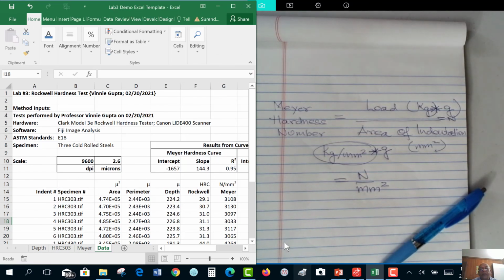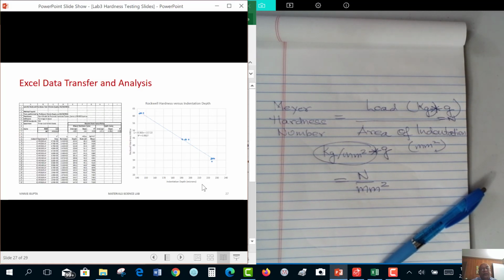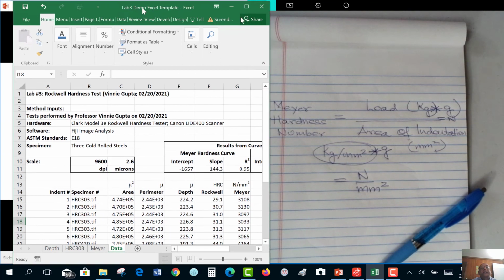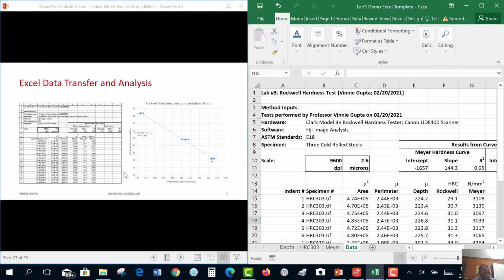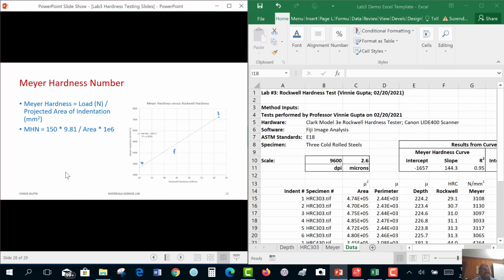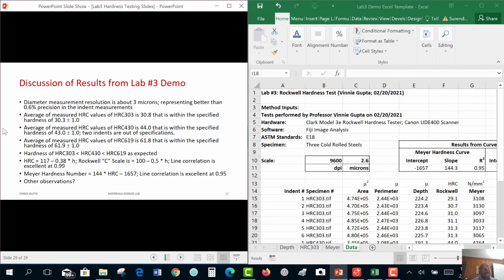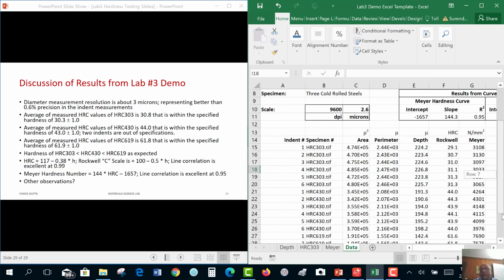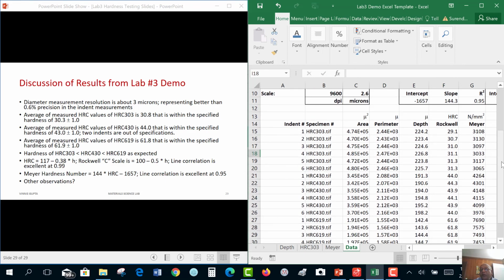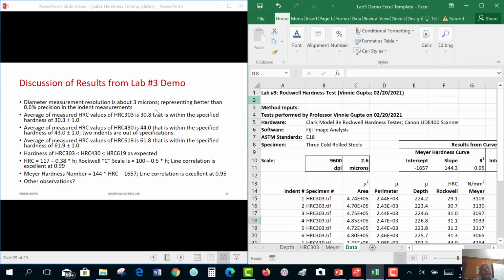Okay, so let's discuss these things. So we did Rockwell hardness versus indentation depth. I defined Meyer hardness number. Here is the formula. So we have a diameter measurement resolution of about 3 microns. Okay, and notice our diameters we can calculate using this perimeter value, and you can find the precision. So the precision is very good, less than 1%.